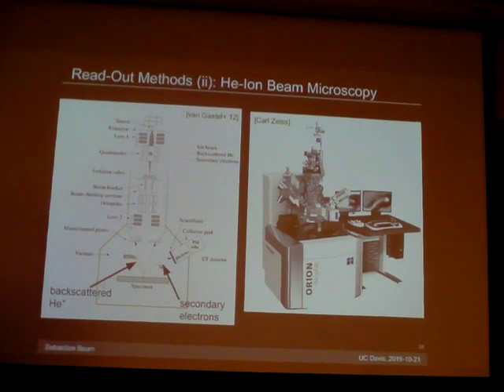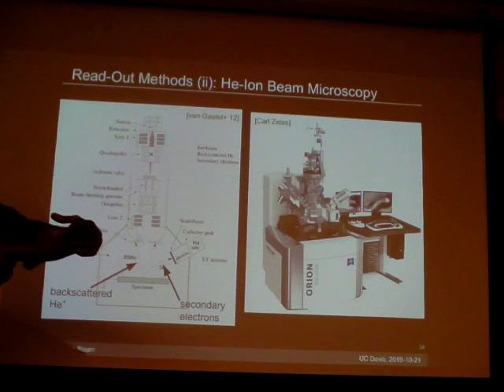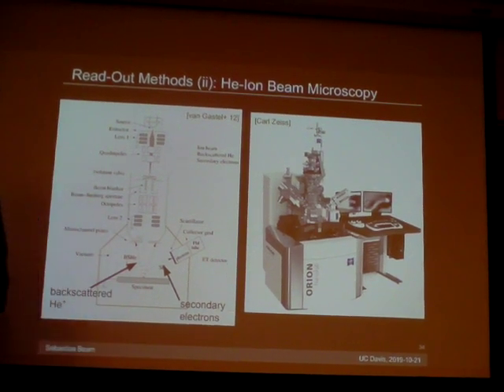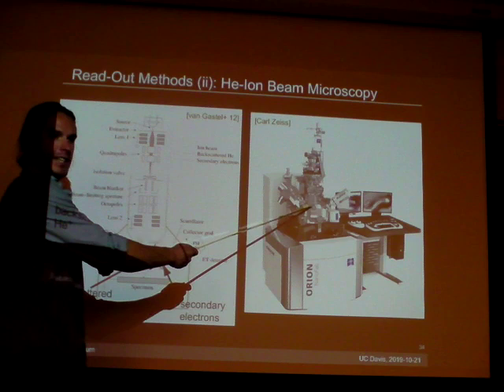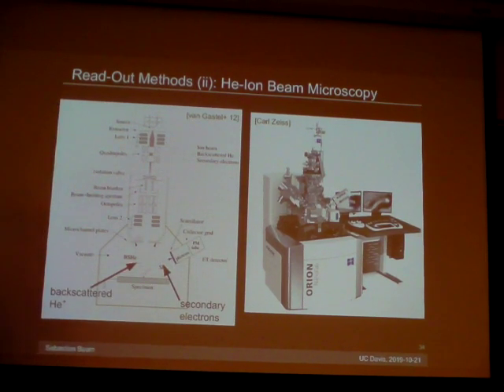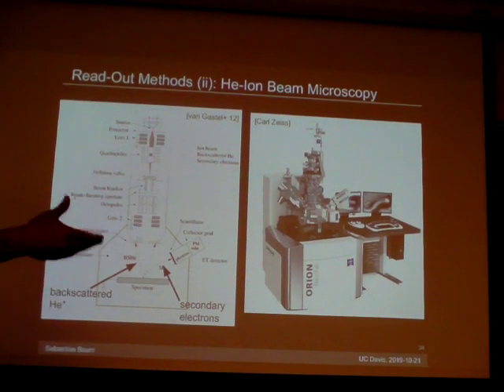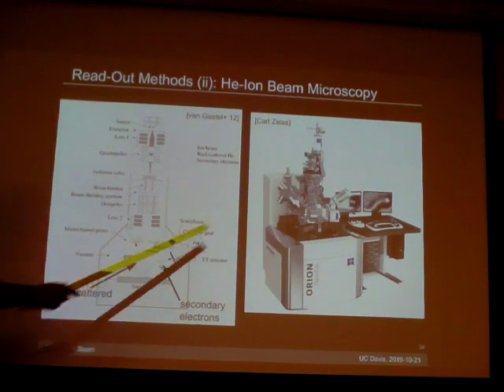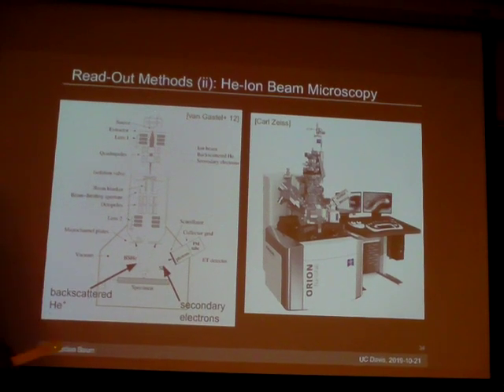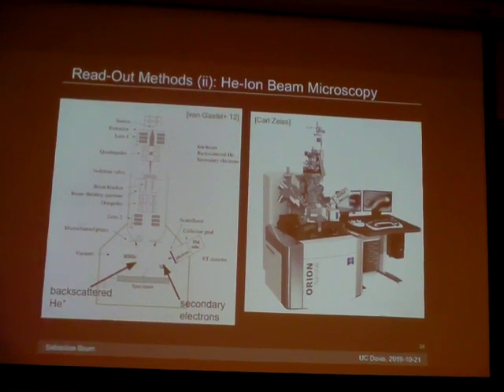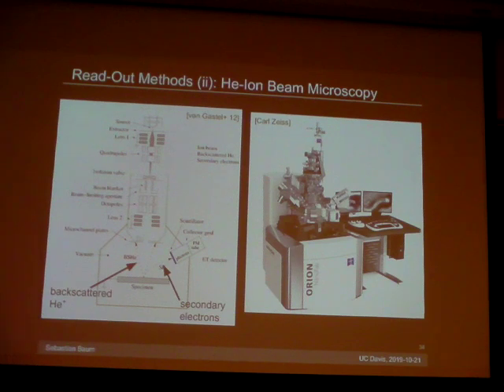The idea we have for this is you take this helium ion beam and you read out your surface to a depth of something like 100 nanometers. And then this machine comes with other ion beams, higher Z ion beams, and you can use these to mill away the surface you've just read out. And you can do this in a very nicely controlled way so that you don't damage the next surface. Now that's very slow, so what you would actually do is you strap a pulsed laser to this, and the pulsed laser can get rid of most of the surface much quicker. It also heats it up a little bit, so the last layer you would have to do with the higher Z ion beam. But that's sort of the rough idea.